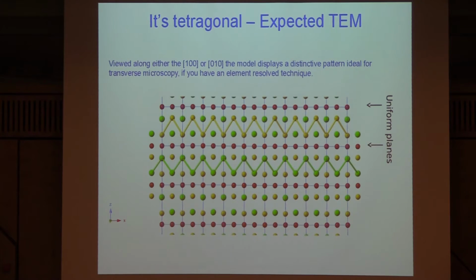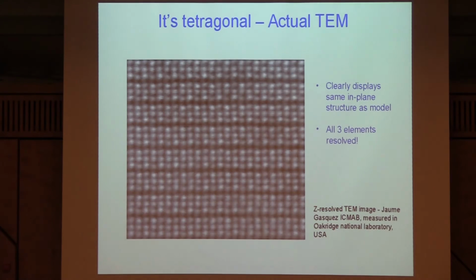Okay, so since we've got a model, we can now model what a TEM might look like, and it's very characteristic actually. You've got these copper planes here, and then you've got this zigzag pattern with the arsenic. So if we have something that's Z resolved, if we can see the atomic number of the atoms, then we can actually see this pattern and confirm our structure. And this is beautiful work, again by Jaime Gasquez of Oak Ridge. He's kind of busy in this game. And you can probably see, maybe you can't, I don't know, but I'll show you other pictures anyway. There's a nice zigzag pattern going on here and the planes here.